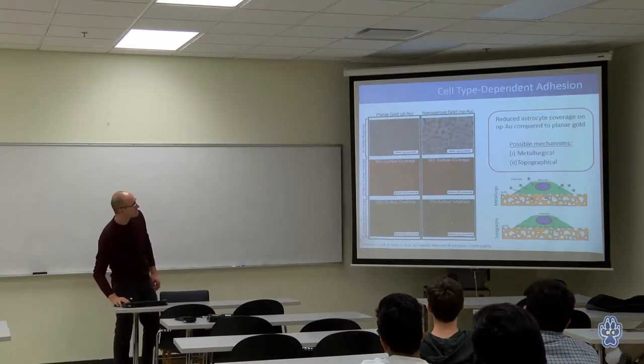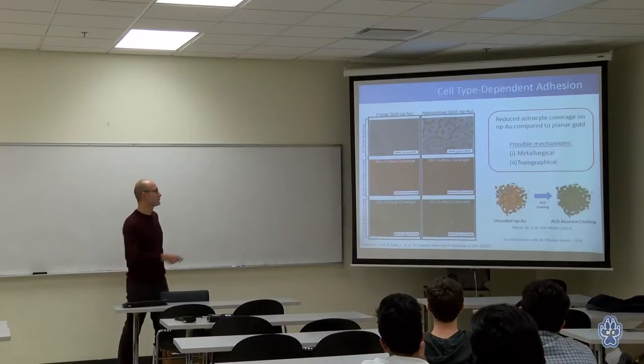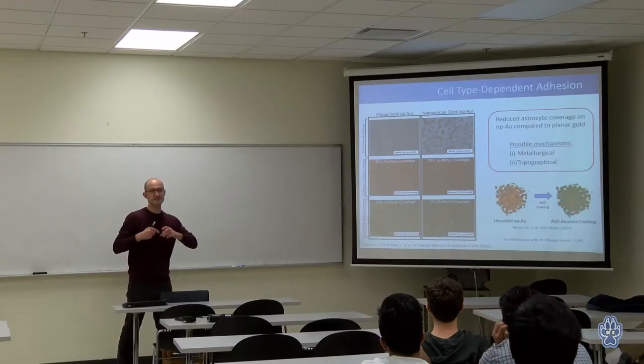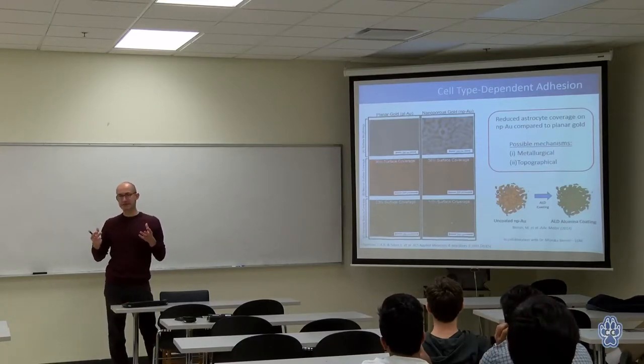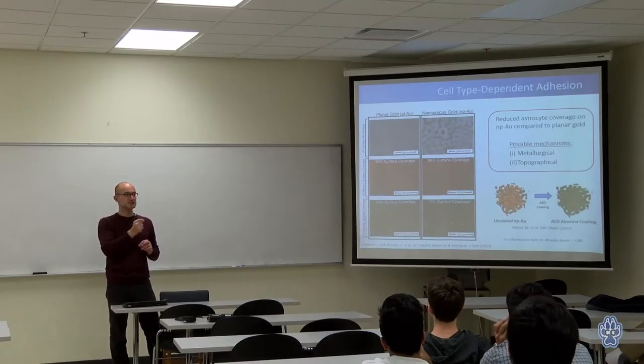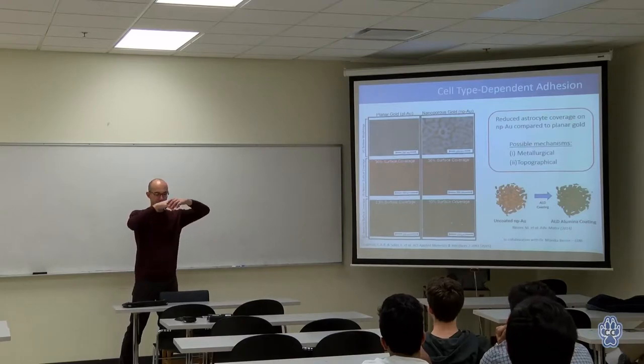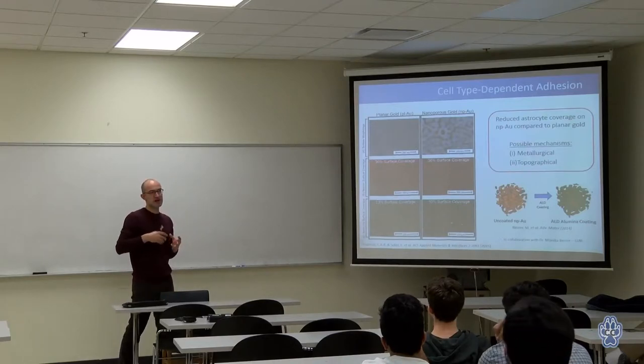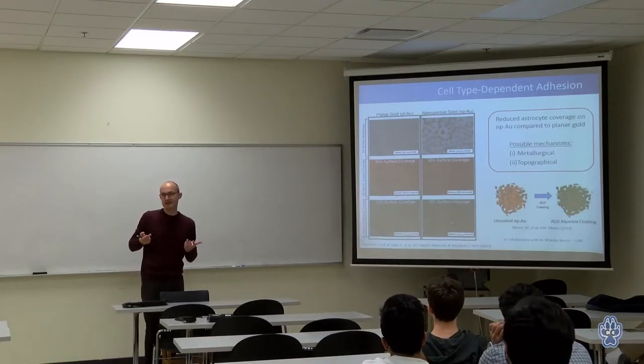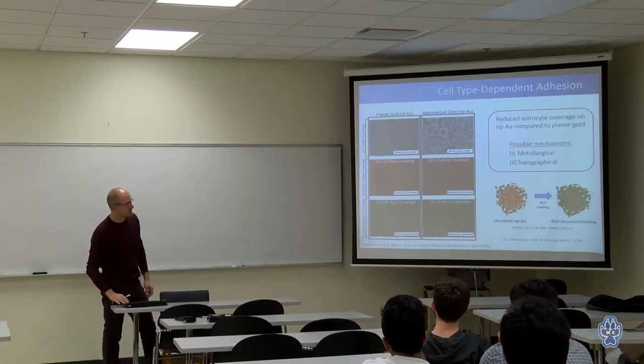So in order to decouple that, we used a method called atomic layer deposition. So this is basically a vapor-based method that can create a very thin insulating shell on a surface. So when you do that, you basically create that shell on the porous gold, which now cannot, if there are any trapped silver ions, they cannot come out of the surface.